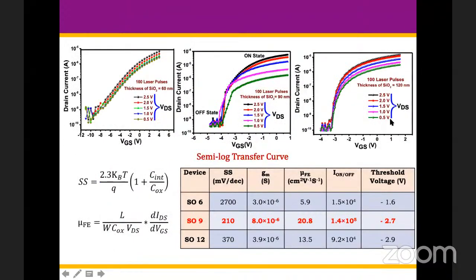And the threshold voltage we can check here. These are the semi-log graphs of the transfer characteristics, same as we showed in the previous one. These are the linear ones, and these are the semi-log graphs, and these are the transistor parameters which have been obtained. You can see the mobility here is around 20. The on-off ratio, for the switching transistor, we can make 10 to the power 5, and the threshold voltage is minus 2.7.